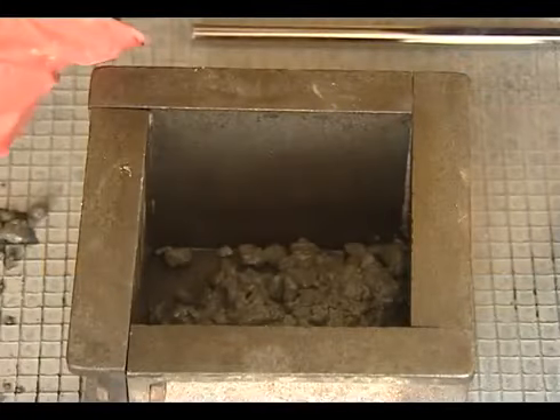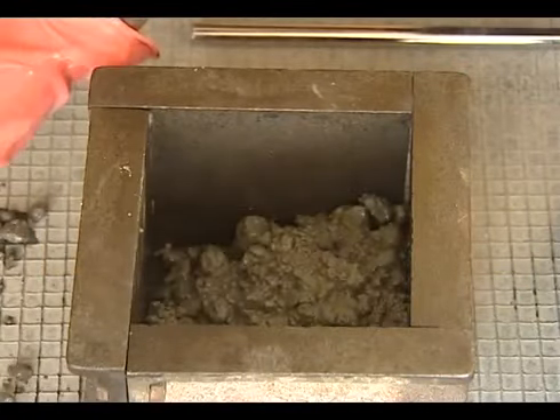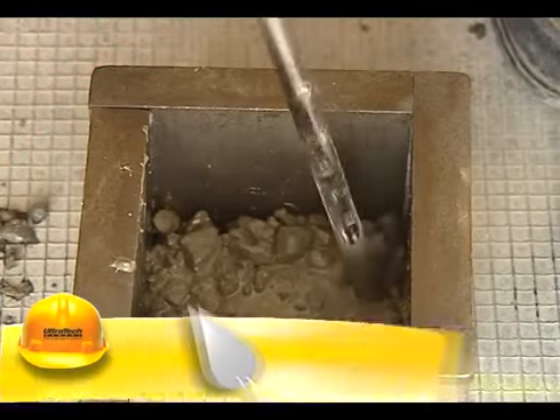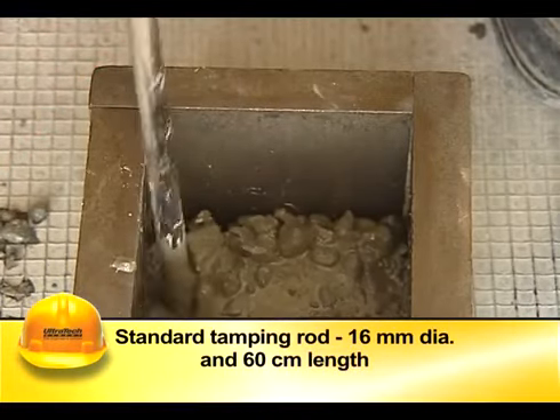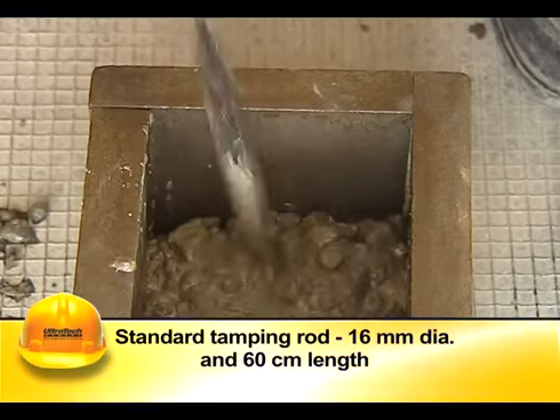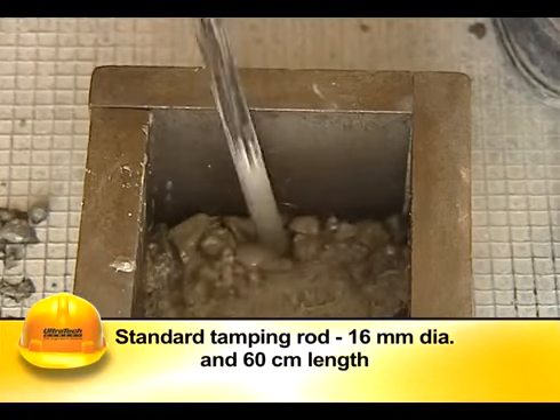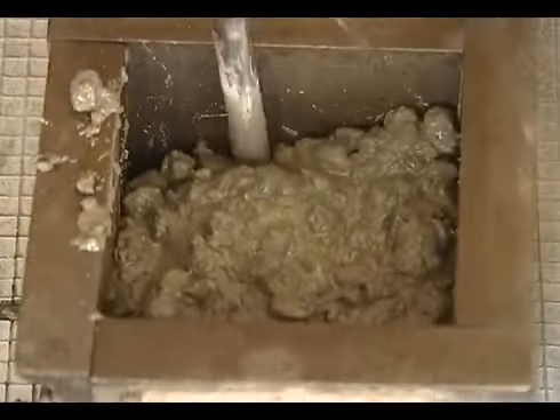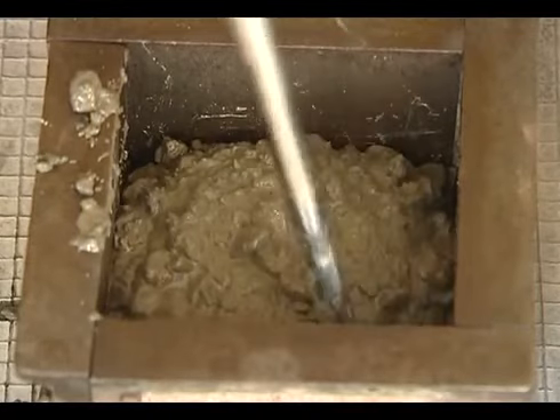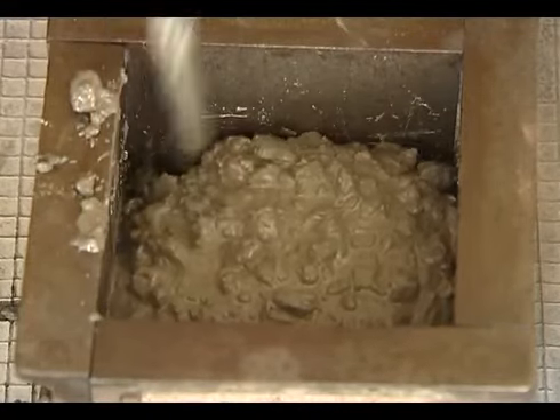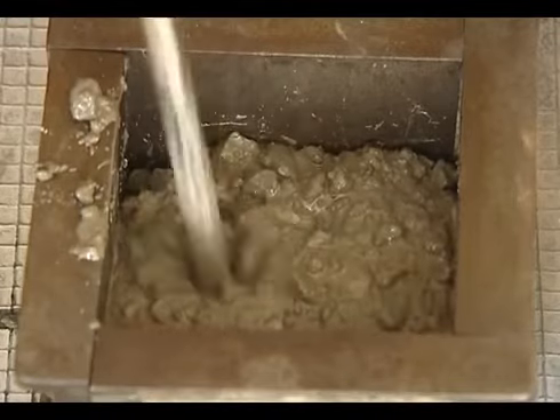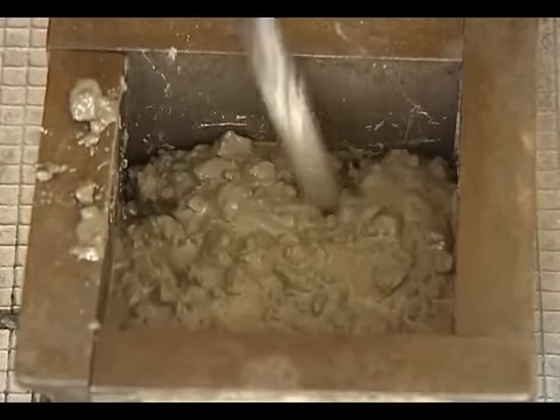The cube is filled with fresh concrete in 3 layers and compacted well using a standard tamping rod of 16 mm diameter and 60 cm long. Each layer should be compacted with 35 blows. The tamping rod should enter the previous layer while tamping the subsequent layer.